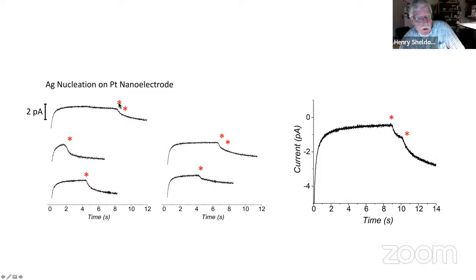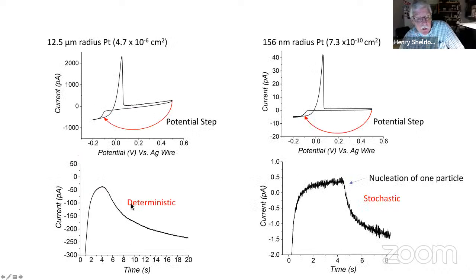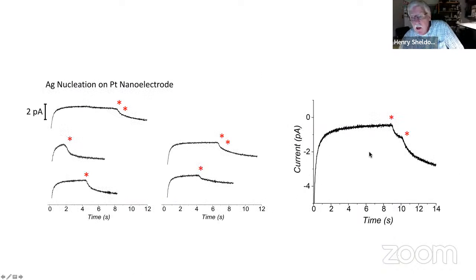The beautiful part about this is you can immediately measure where nucleation occurs when you only have one particle and you're using a small electrode. If you're using a big electrode, you can't tell where the nucleation is occurring. You can model it mathematically, but you can't measure the actual points in time where the different nuclei are forming, okay?